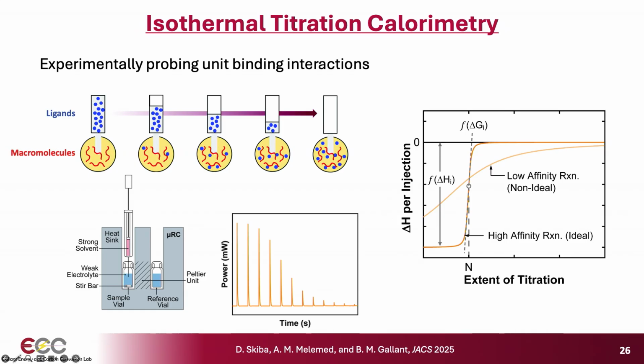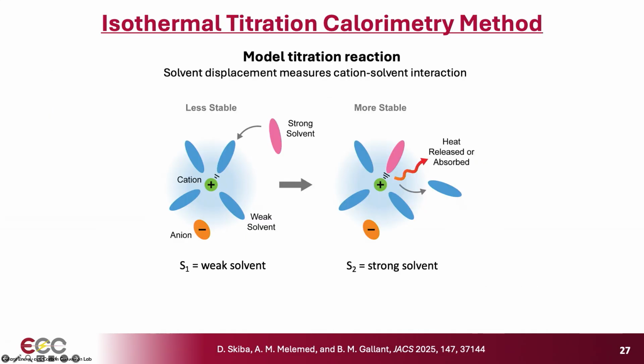And for a high affinity reaction, you have a sigmoidal curve like this. And that allows us to actually determine or decouple the delta G of the interactions, delta H, and also N, which is the stoichiometry of the interaction between ligand and macromolecule. If we have a low affinity reaction, we'll get a response that looks something like this. Still informative, but we need to do more work to be able to decouple the parameter.